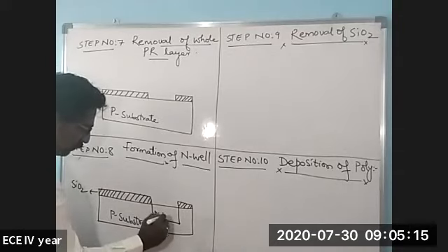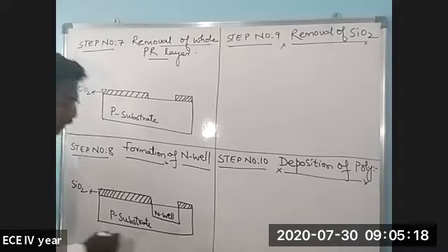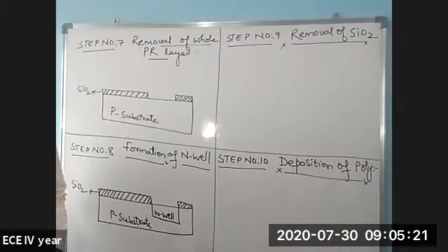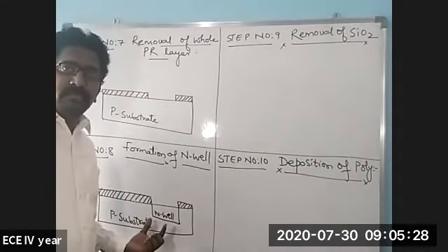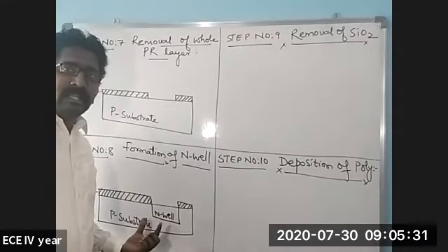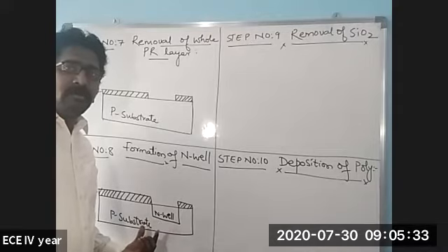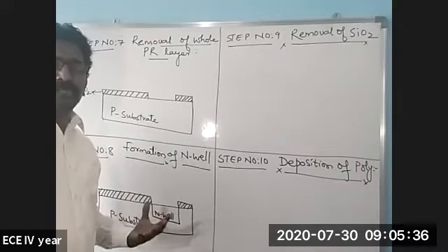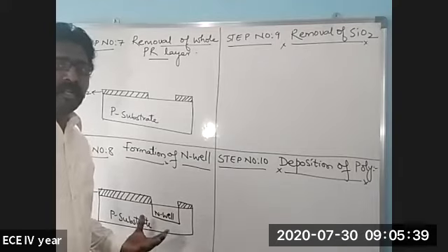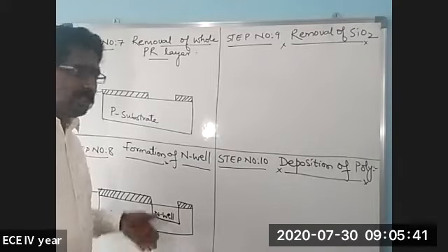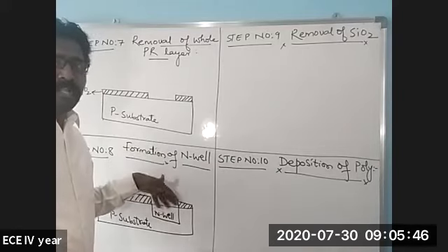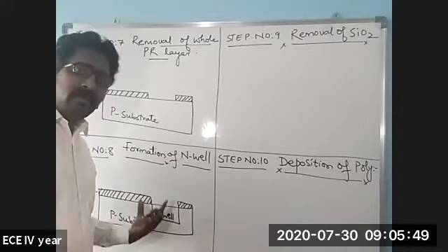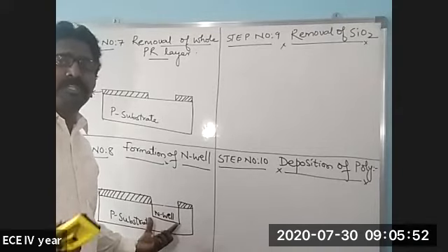And this is the N-well. N-well is nothing else but a region created by diffusing of N type of impurities. That diffusion will be done by passing a phosphorus gas or PH3 gas at very high temperature, and that entire substrate will be subjected to high temperature, and at that particular temperature, the N type of impurities will be diffused here, and that region will act as an N-well, and now this N-well will act as one type of substrate to another device.